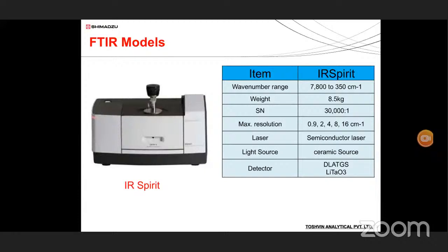The signal to noise ratio is around 30,000 to 1, which is the highest in its class. The maximum resolution for this IR Spirit is 0.9 to 16, but by default we use 4 centimeter inverse. If we increase the resolution from 4 to 0.9, which is the maximum resolution, the noise of the spectrum automatically increases. So to avoid this noise, we recommend running the sample at 4 centimeter inverse resolution.